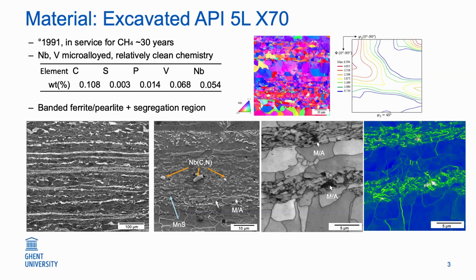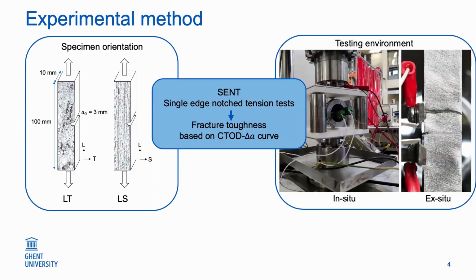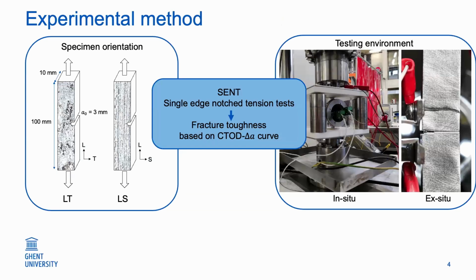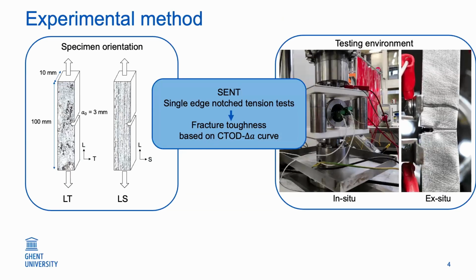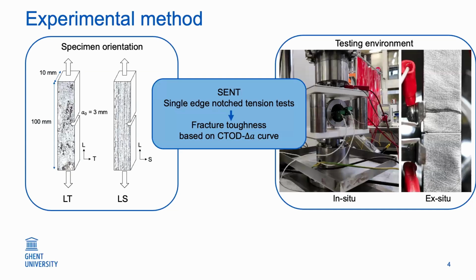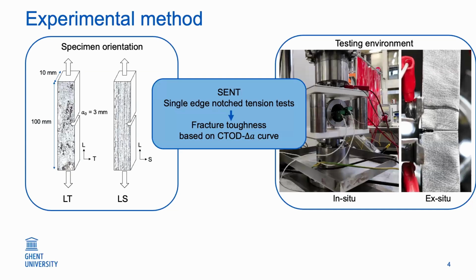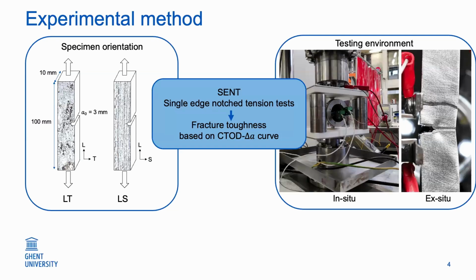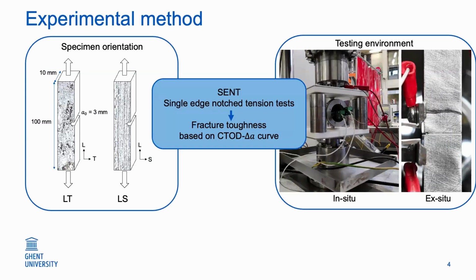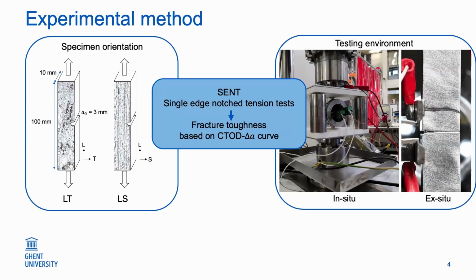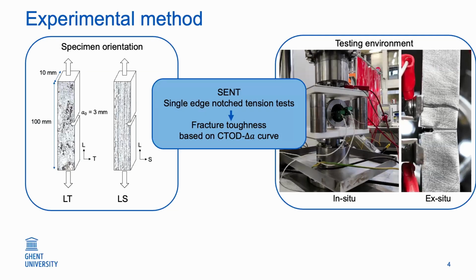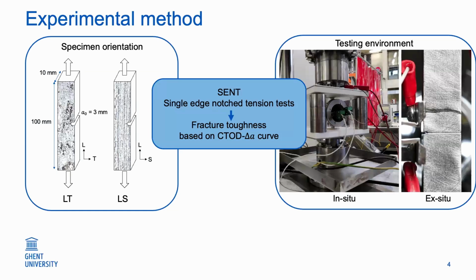So some interesting microstructural elements that can be quite dangerous in the segregation region. For experimental methods, I worked with the single edge notch tension specimens, the SENTs, I will call them for short. And we actually tested two orientations. So we put the notch either along the bands or perpendicular to the bands, which I've named here LT and LS. So the crack will grow actually in the T direction or the S direction over the pipeline.